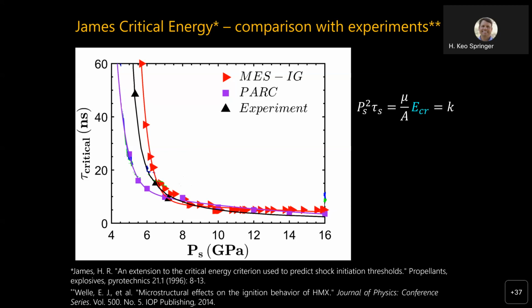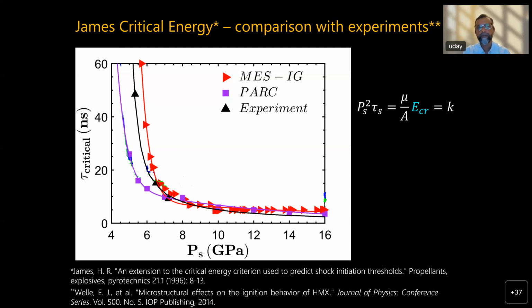The void-void interaction part is, in my estimation, inherently learned by PARC. Whereas in the MES-IG model, we have to have another surrogate model, which we have, and we have to insert it into MES-IG, which we have done in order to get these curves. So in MES-IG, we have to make an effort to include void-void interaction because it relies on single void calculations, whereas because PARC relies on a full DNS, and the full DNS already has the void-void interactions in it, I think PARC actually takes that into account.